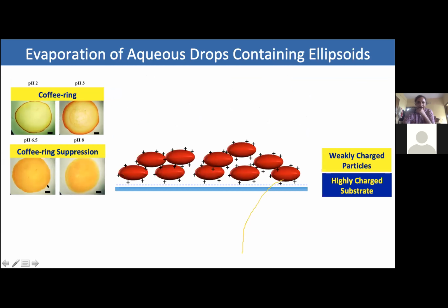Now, if you have a case where the particles are weakly charged and the substrate is highly charged, then there's a deposition of more and more layers of particles on the substrate, and therefore you don't have any free particles left in the fluid. Even though there's capillary flow, the particles are stuck to the substrate, and therefore there's no deposition of particles at the edge. So a strong particle-substrate attraction is what leads to the uniform deposition of colloids in this case.